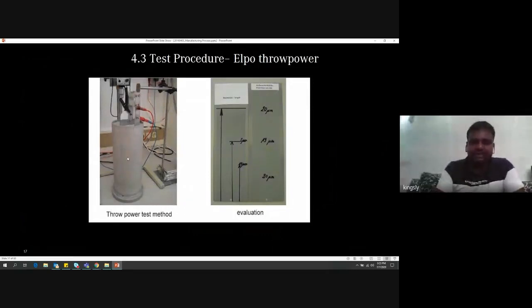These are all test methods. For example, when we put 1 bar pressure, how much throw power are we achieving, and by this, how much coating are we getting, so how many microns in thickness. Basically, this is like a complete car body. We make a sheet of 100 millimeter or 1 meter square. Then we put this plate into the tank, give the circulation and voltage, and check how many microns we are achieving. For example, here we are achieving 20 microns, in the middle of the plate 19, and the edge of the plate 20 microns. So more or less we know it is within tolerance, because for e-coat we need 18 to 20 or 25 microns. Then this throw power is okay.